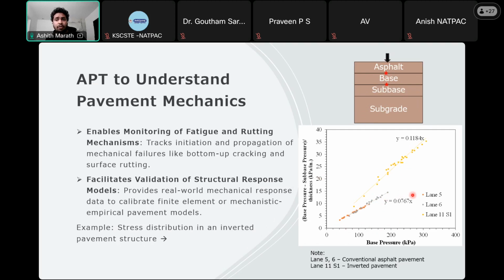All three lanes have the same base layer material. But because of the CTB layer below the base layer, the modulus of the base layer is different with respect to the pressure experienced by the base layer material. So with this kind of analysis, we are able to use better models for our pavement response prediction, and also for our back-calculation procedure using the FWD testing.